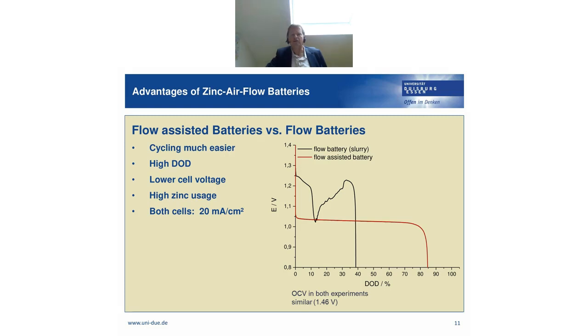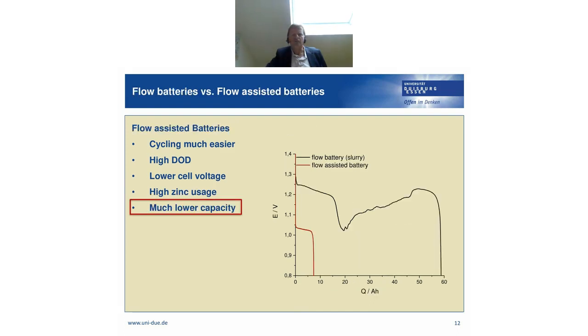And also the cell voltage levels are different. The flow-assisted battery has a lower operating voltage, but a long plateau until a large DOD is reached. So the characteristics are really a little bit different. And what is most striking, of course, is that the capacity in amp hours is much higher for the flow battery. As I've said to you, we have 50 weight % of zinc in the slurry, and we have, of course, less zinc available for the flow-assisted battery experiment, which is only around 8 amp hours. So this is the advantage of using flow batteries with slurries.